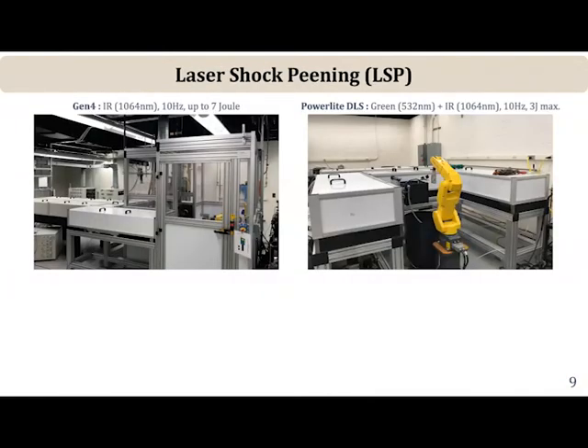Okay, so we have in the Ohio Center for Laser Shock Processing in my former institution, UC, 2 systems. One is a Generation 4 system. These were built by Continuum, and they were custom built, patterned along the systems that GE Aviation has in Cincinnati. And in fact, we got a lot of help in building these systems from GE. So this is a 7-joule system in each leg. It's infrared, at a frequency of 10 hertz, and the pulse width is around 20 nanoseconds or so, with a robot system and a cell for the water and all the safety measures and so on.